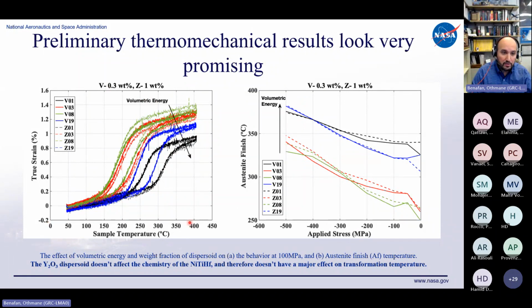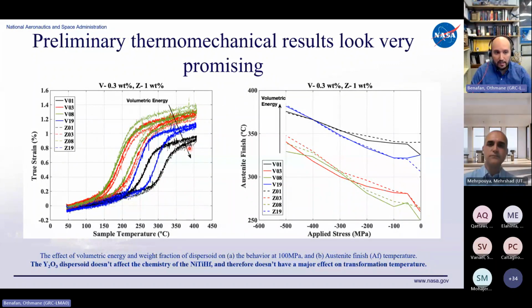Observation number one is that the V series simply means a different dispersoid volume fraction. We wanted to know, if we put X amount of dispersoids, do we affect the transformation temperatures or the mechanical properties? If I look at just the black curve here, the heating and the cooling, there are actually two plots on the same curve because they overlap. What we show here is that the mechanical data is nice and not ideally stable just yet, but looking very promising as far as stability.